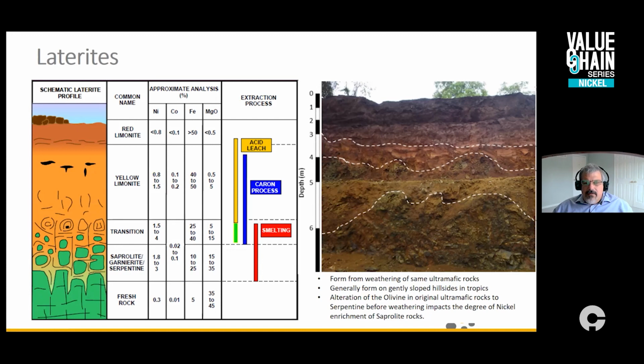In the top of the profile, once the MgO is gone, the nickel becomes soluble without the presence of MgO. That nickel gets dissolved into the water and then descends into the profile. And then once it hits the saprolite layer, the nickel precipitates out and more MgO is removed, and that process continues and continues, and that profile grows. So what we see in the saprolite profile that's directly on top of the fresh rock is nickel grades that can range from 1.5 to 2 or even 3 or 4% nickel.